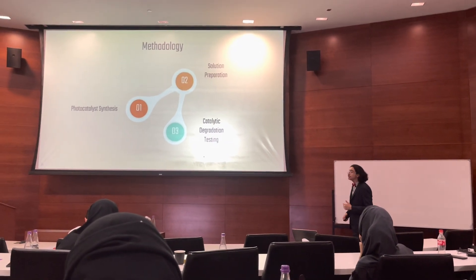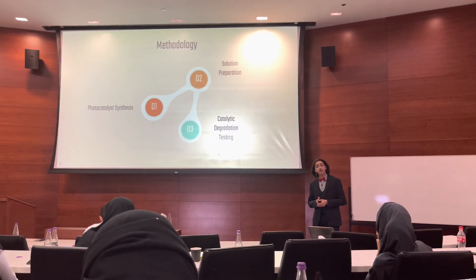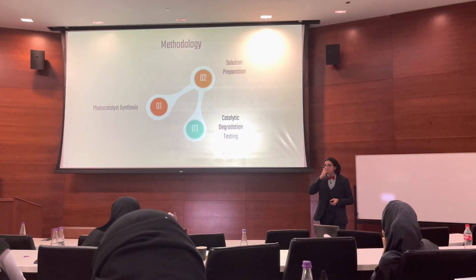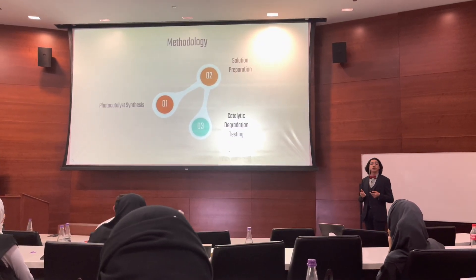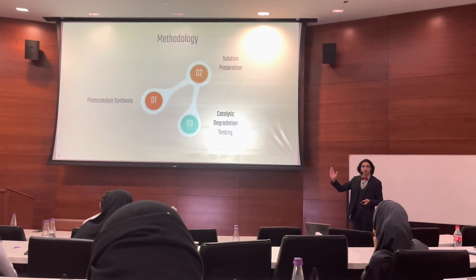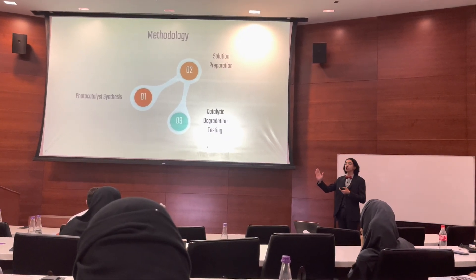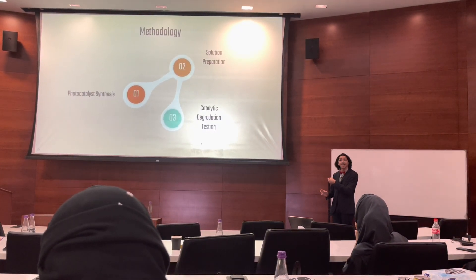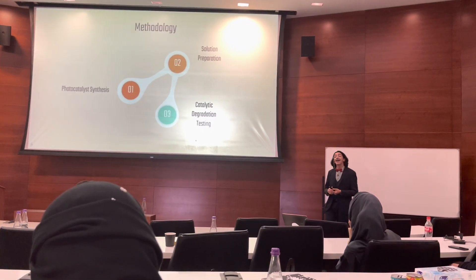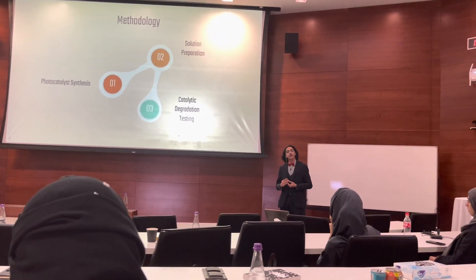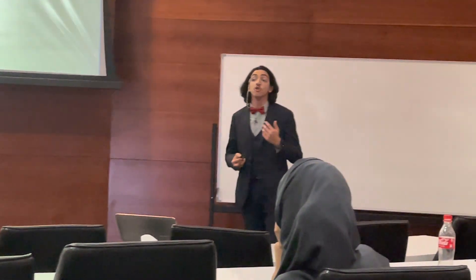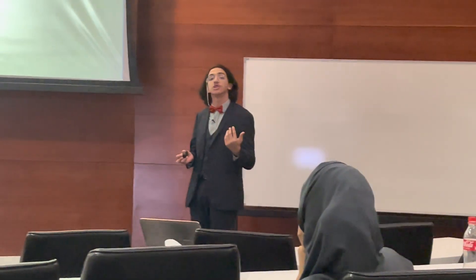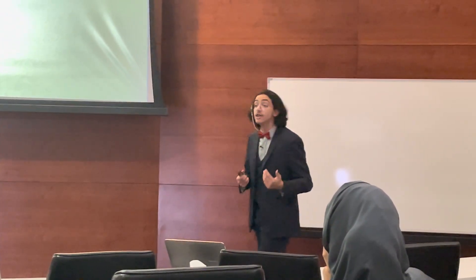To test catalytic degradation, one technique I used was UV-vis spectrophotometry. This technique measures the absorbance of a sample — in my case, the solution with dissolved pollutants. You strike it with different wavelengths of light and measure how much is transmitted versus absorbed. Using a well-known chemical law, you can determine exactly what concentration of pollutant remains in solution. This allowed me to map out the progressive degradation of dyes over time.